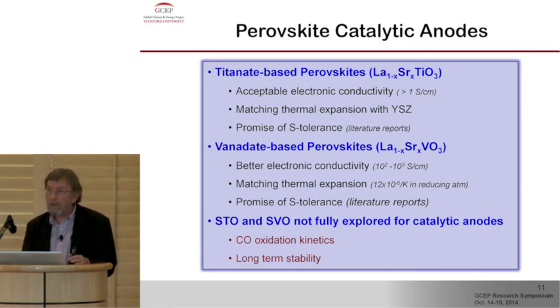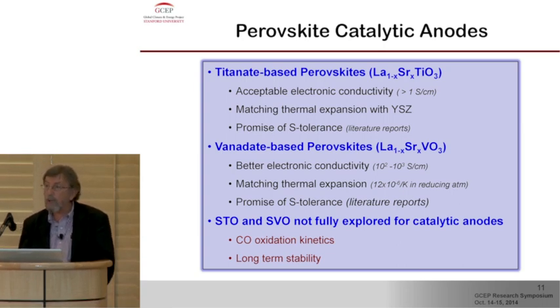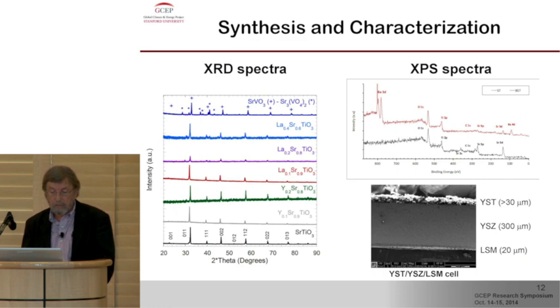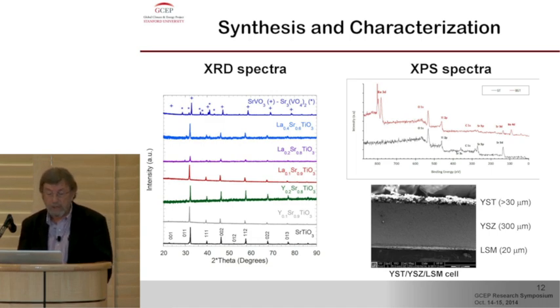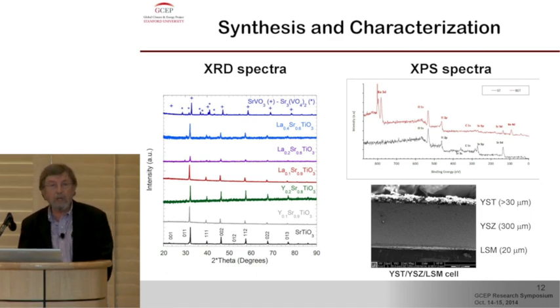They have good electronic conductivity. They have reasonably matching thermal expansion coefficients, so we are hopeful that these will be a step forward in that direction. We already started making and synthesizing these, doping on the A side as well as on the B side, and characterizing them with XRD and XPS. I'm not going to go over all the details. And we started putting them into cells and making what we call MEAs, the membrane electrode assemblies.